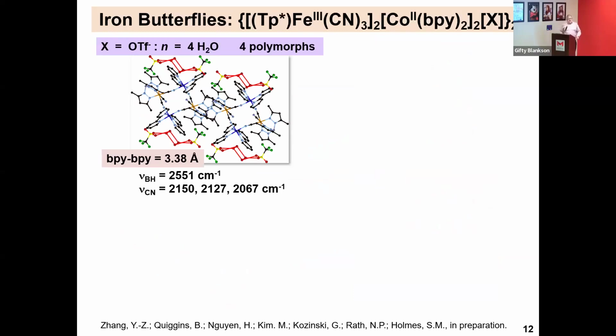All right, so in terms of compounds that have tris(3,5-dimethylpyrazolyl)borate, star, 2,2'-bipyridines on the cobalt, and some anion, X, in the presence of 4 waters of crystallization, these water molecules can adopt various interactions with the anions, charge balancing the complex. They can hydrogen bond to the cyanides. They can hydrogen bond to themselves. This is one polymorph. Polymorphism is a very important issue for pharmaceutical companies because the bioavailability and dissolution kinetics depend on how fast or slow the crystals go away in the body.